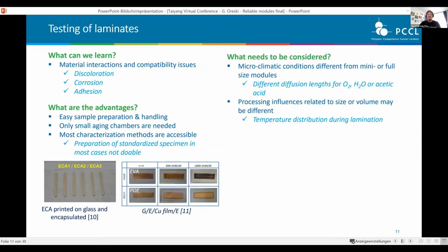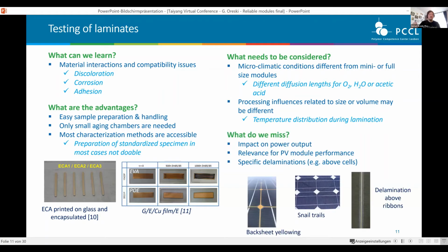What needs to be considered: even though we have the encapsulant, backsheet, glass structure, the microclimate is still different from full or mini modules, because we have different diffusion lengths for oxygen, water vapor, or, in case you use EVA, for acetic acid. And the processing influences related to size or volume may be different. So what do we miss? Still a lot. We cannot measure power, so we may see discolorations or effects, but we don't know their impact on the power output or their relevance for PV module performance. And we still miss some very specific delaminations, for example, when we put in full cells and have this delamination above ribbons, as shown here.